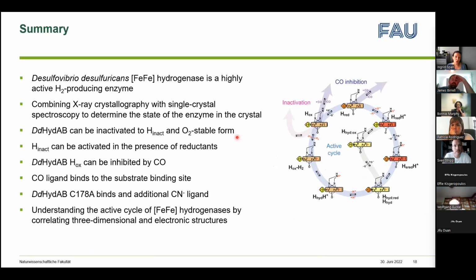So far, we've been able to show that DDH can be inactivated to form the H-inact state, which is stable towards oxygen. The state can be reactivated in the presence of sodium cyanide and hydrogen. We also could determine the structure of H-ox that has been treated with carbon monoxide, and we show that the CO ligand binds to the substrate binding site, and we see that a variant, the C178, binds an additional cyanide ligand at the open coordination site.